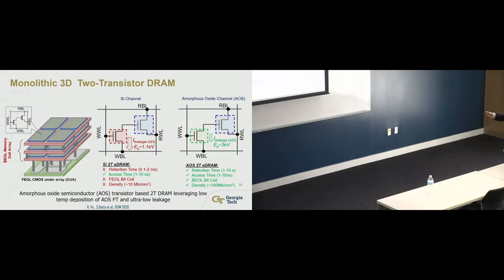So one of the things we are working on using the clean room down here is to take advantage of our amorphous oxide semiconductor. The beauty of that material is it has a 3 eV band gap. It goes down at low temperature, and we can actually reduce the leakage of the transistor down to about a femtoampere of leakage. A femtoampere is basically 10 to the minus 15. Ideally, we would like to go to attoampere, 10 to the minus 18. You're literally dealing with losing a few electrons per second. You can do the math.